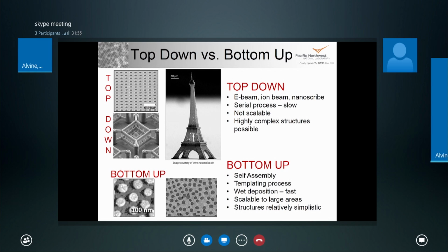So we can make these self-assembled structures and use those as templates, or potentially just use the self-assembled structure as it is for the nanoplasmonic structures. Because these use wet deposition, they're usually very fast and scalable to large areas, and they also mesh with manufacturing techniques that are already out there. The drawback is that the structures you make through these methods are typically very simplistic. So I'm hopefully going to give you some examples of the structures you can make, and maybe some ideas of how to make them more complex for improved functionality.